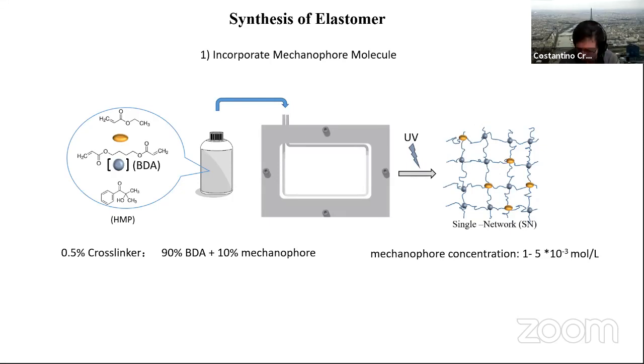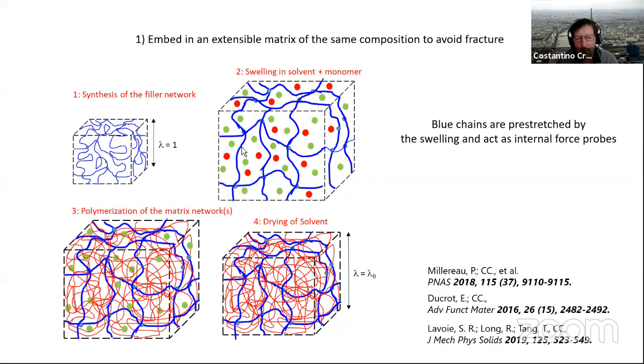So initially what we did is we used the technique of embedding, the multiple network system. When we synthesized this network, we had a swelling step in solvent and monomer. Then the monomer of exactly the same polymer can be polymerized. Here I'm showing a red and blue color just to show that it's two different polymerizations, but it's actually exactly the same material, but the blue chains are pre-stretched. It's a bit like taking a continuous filler of fibers and putting them into a matrix. The matrix comes in, extends the chains of these fibers in all three directions. So it's isotropic. The advantage of this method is that you can break some of these blue chains without breaking the material. So we can follow, for example, the activation of the mechanophore, like having an internal probe inside of the material.